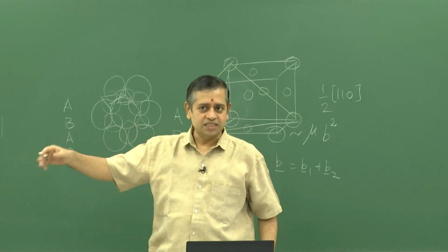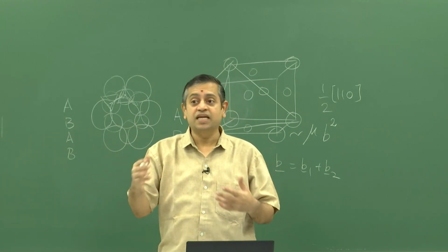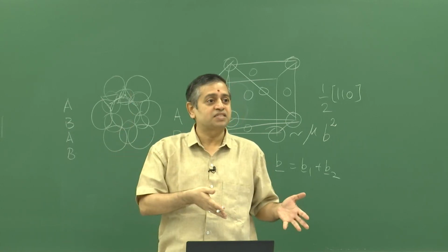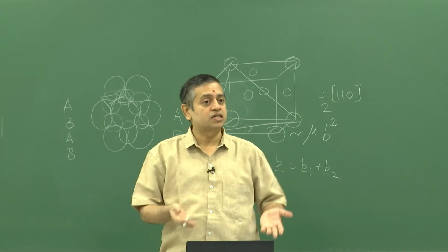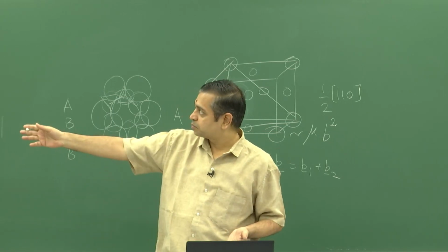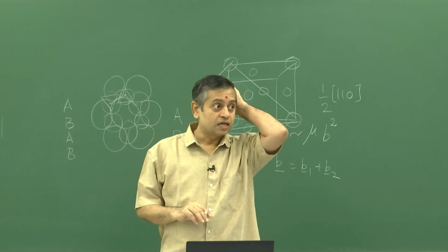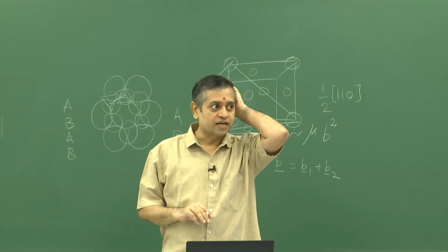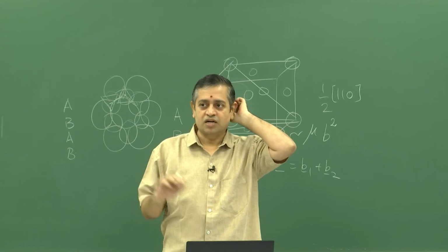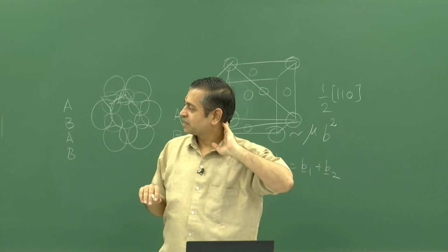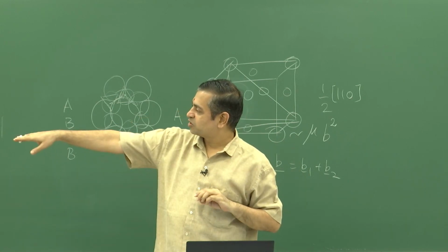So, at low temperatures it does go into this HCP phase, which is an indication that the stacking fault energy has become negative. It goes down and then it becomes negative, then the system will spontaneously undergo a phase transformation. Okay, that is what is happening. So, that is why this is a model system. Cu3Al, yeah, some ordered structure, which is also of interest. Okay. But we will not talk about it. We will only talk about the low temperature.